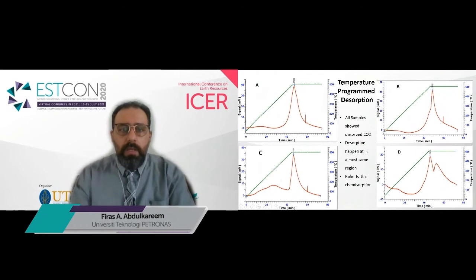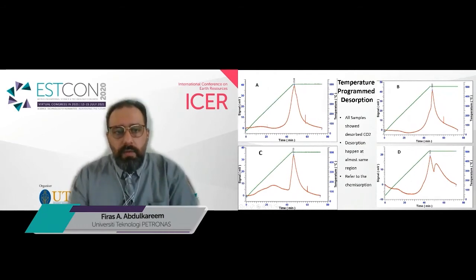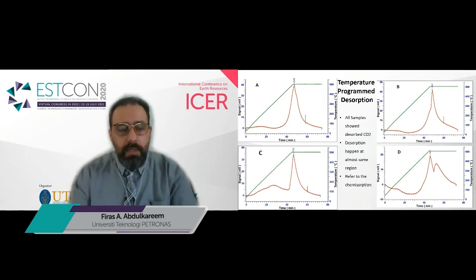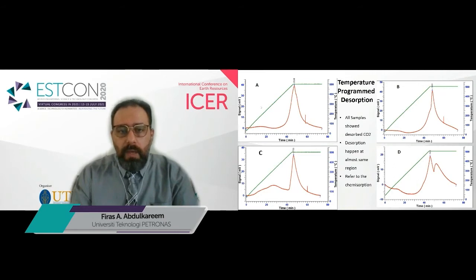In terms of the temperature program desorption, we can see that usually there is some desorption of CO2. For those who are not familiar with this process, the samples are usually regenerated or pre-treated by purging with nitrogen for a while, and then CO2 is injected into the sample. Then after almost 1 hour or 2 hours, once the sample has achieved some equilibrium with that CO2, the CO2 injection is stopped, and the heating process starts with a mild injection of helium, and the outlet of the desorbed or regenerated sample is collected and analyzed by some TCD or GC connected online to the process.